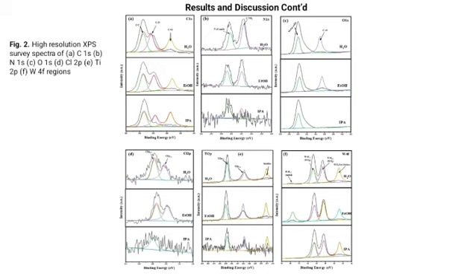And these peaks were observed at 530 electron volts, which is assigned to the metal oxide bond, and the other peak at 534 electron volts due to carbon-oxygen interaction, which was observed to be weakly interacted in the isopropyl alcohol-based material. For the chlorine 2P spectra, all the materials demonstrated an intense peak at 198 electron volts, which is assigned to the chlorine 2P 3/2 spin interaction due to chloride ions, while the chlorine 2P 1/2 peak, appearing at 200 electron volts, was also weakly observed in the isopropyl alcohol-based material.